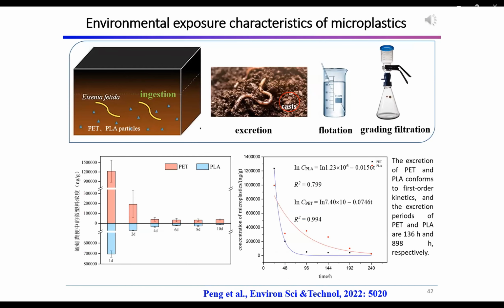Although submicron and nano-sized particles were hard to identify by microscopy, their occurrence could be measured by LC-mass spectrometry. In comparison to the mean concentration of macroscopically recognizable PET in the cast during the 10 days of excretion, the amount of submicro and nano PET polymers was much lower. Differently, the mean concentration of submicro PLA was even higher than that of the macroscopically recognizable PLA. This verified that PLA in earthworms is more likely to break down than PET, and a large number of smaller-sized PLA particles might be formed and released by earthworms.